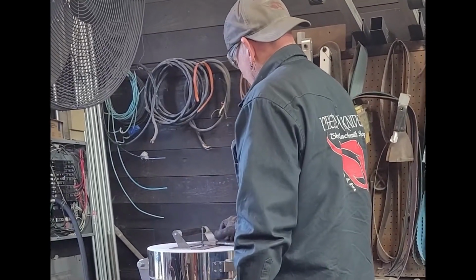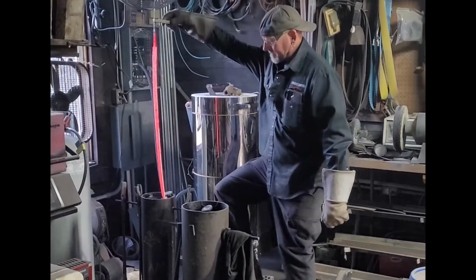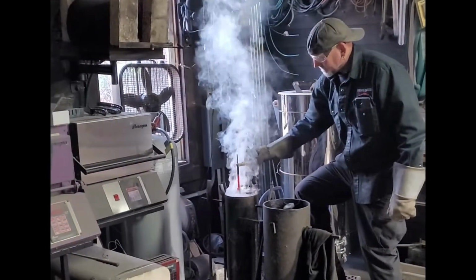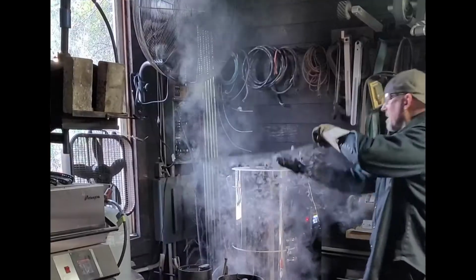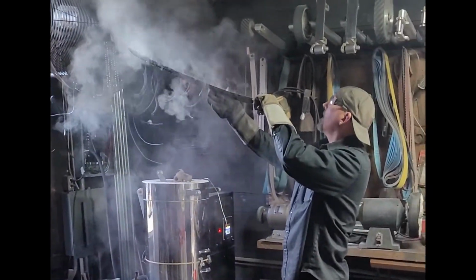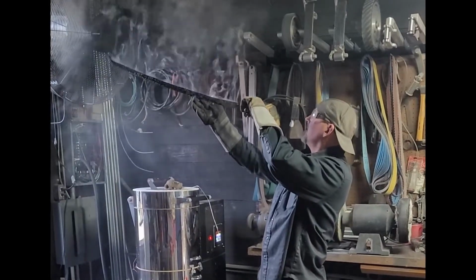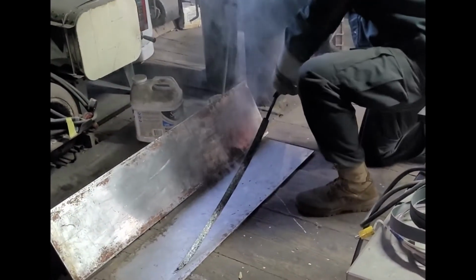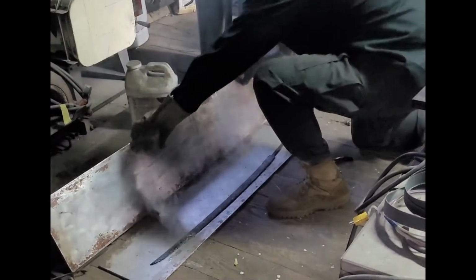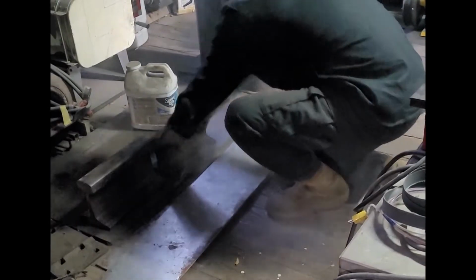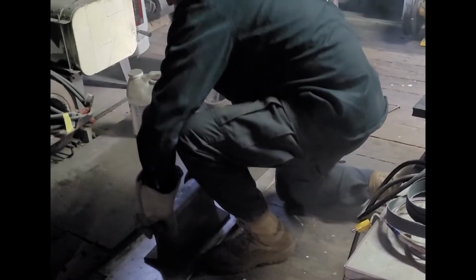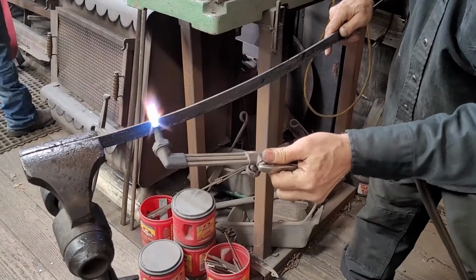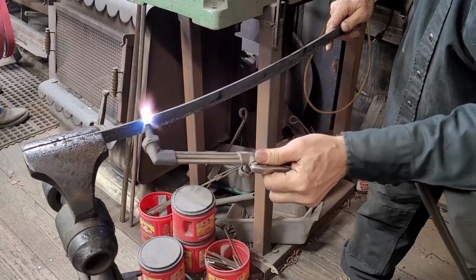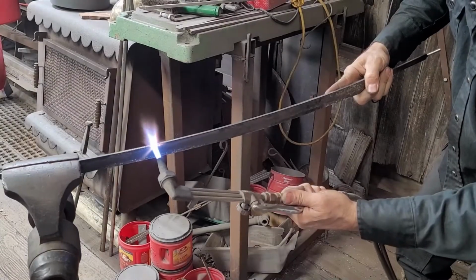The blade undergoes 2 more normalization cycles before heating to temp and quenching into AAA quench oil. To reduce warpage, the blade is pressed between 2 aluminum plates. We still wound up with warpage, so after temper the blade is heated and bent to remove the warps.